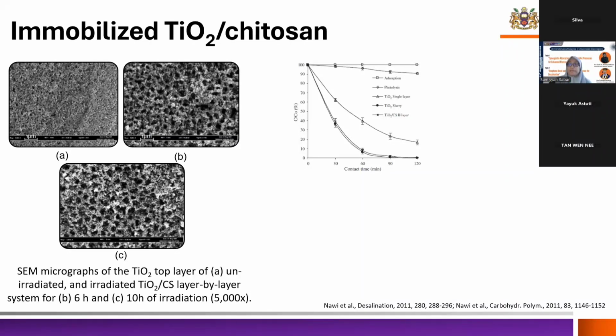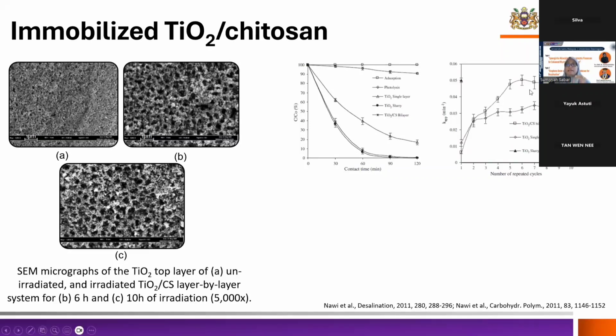And we have also repeated the usage of the same samples for 10 cycles of application, and we can see that there's a consistent degradation of phenol by the titanium chitosan bilayer, and this is way better than the TiO2 single layer. And the TiO2 slurry can only be used one time because it's difficult to recover the powder.